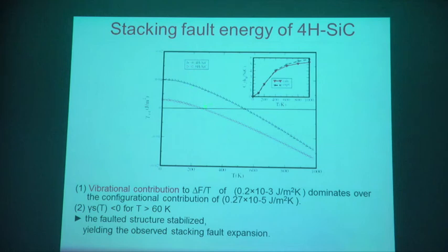And as a result, as you heat up silicon carbide, it will start forming these faults. So although the Toyota researchers made silicon carbide with very low defect density, once you use it in a diode, the temperature goes up and current goes through it, it starts forming these stacking faults. That was the simple explanation of how this happens.